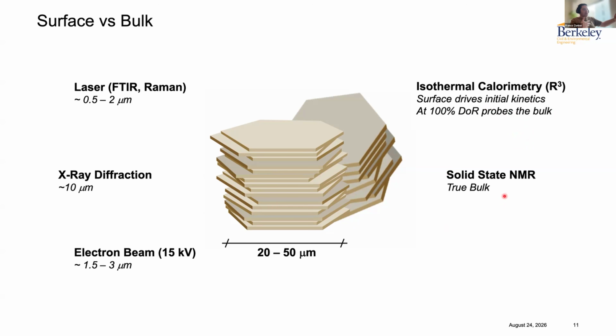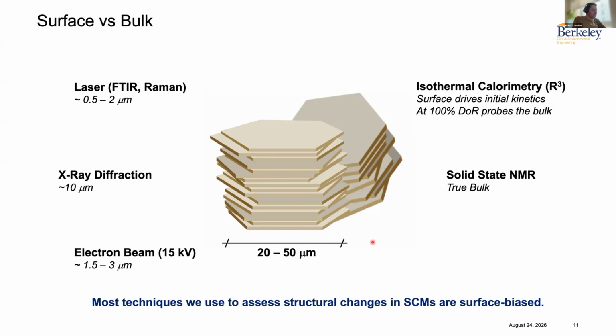It doesn't have this penetration issue that other techniques have. It just samples all the material, all the nuclei that are within that rotor, and returns information back. And I think that many of the discrepancies that we see in the published literature between the classics that we have on the left and the not so classics that we have on the right are in many cases stemming from this surface bias that is not accounted for when the experiments are conducted.